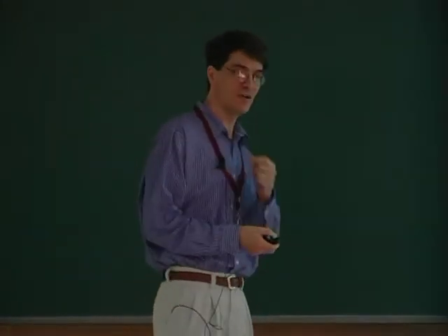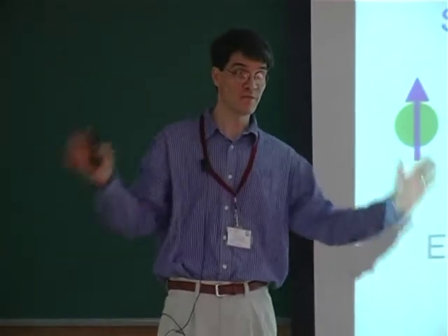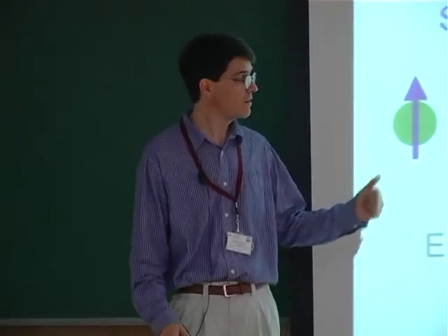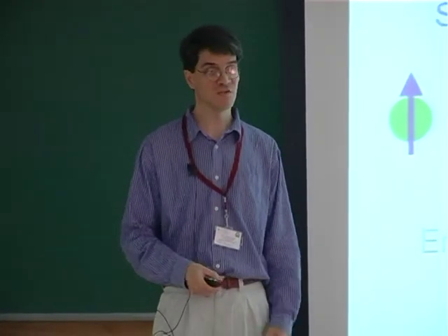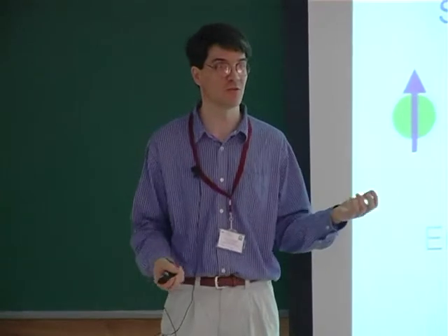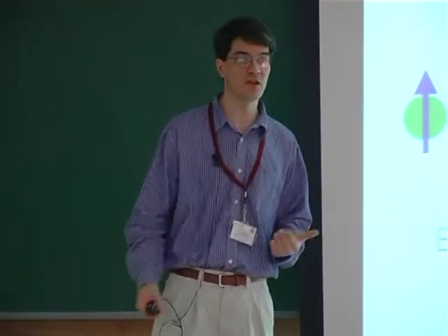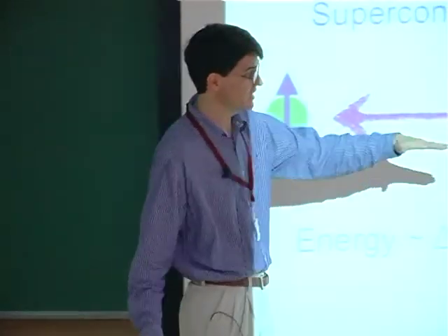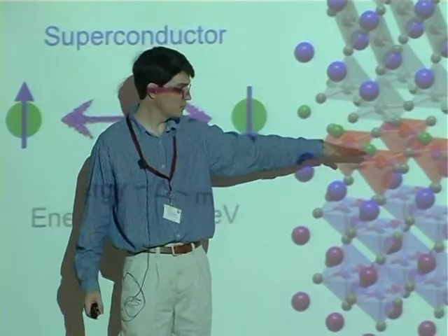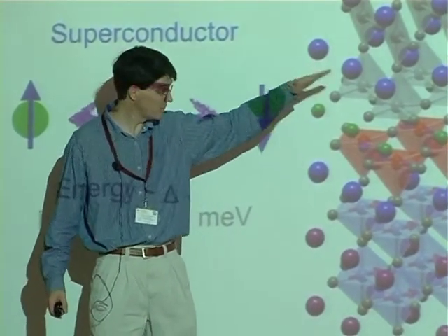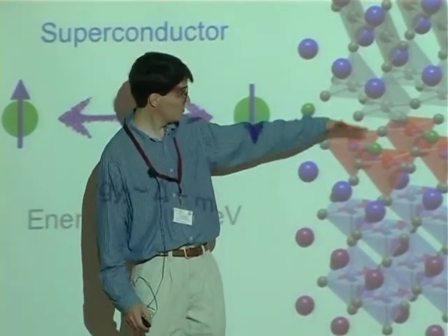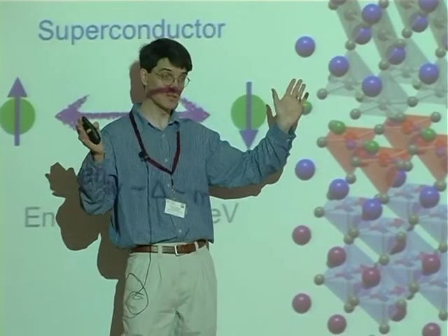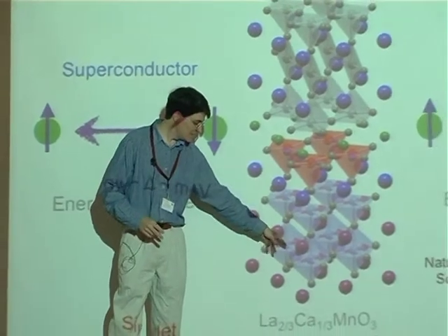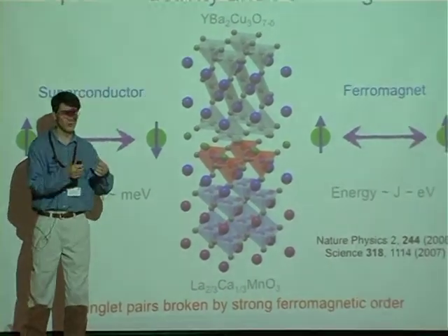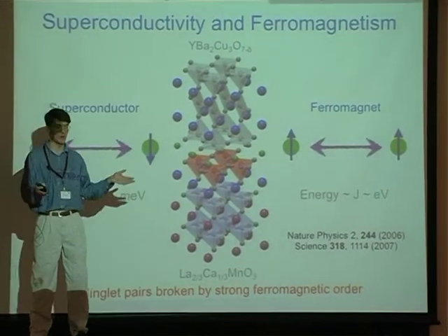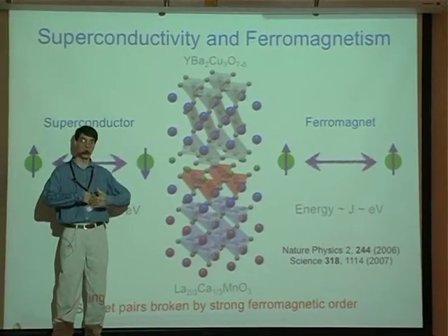Well, actually, I think what you want to do is go away from perovskite completely. I think the problem is you have an octahedra, and it's very hard to impose super large distortions on the octahedra. So what you want to do is go to a tetrahedra, for example. Like in a cuprate, which is what I was going to touch on in this example, you get an extremely large orbital polarization, and you get it for a very simple effect: out of plane, there's no atom there. So it totally changes the crystal field. Whereas in this case, how far am I going to stretch this? I can only stretch this octahedra so much before it's going to fall apart. So I think the paradigm is actually to go beyond that.